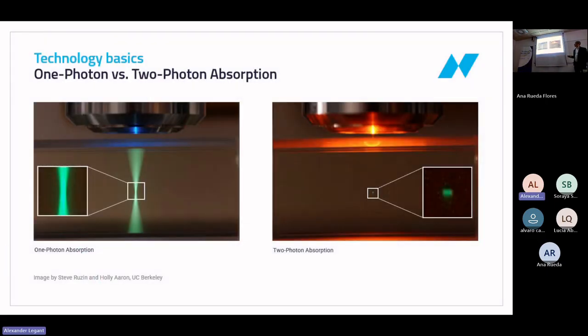So if you just look at the lights on the left side, and for example, if you use a blue laser light, we focus the blue into a fluorescent dye, and you see that the fluorescent dye shows fluorescence along the whole way of the laser through the material itself. Now, if you go to longer wavelengths, like for example near infrared, in most of the volume nothing happens, except at this tiny spot at the laser focus. And the reason for that is that one photon of near infrared doesn't provide enough energy to trigger a chemical reaction.